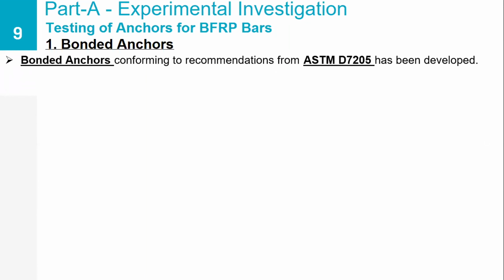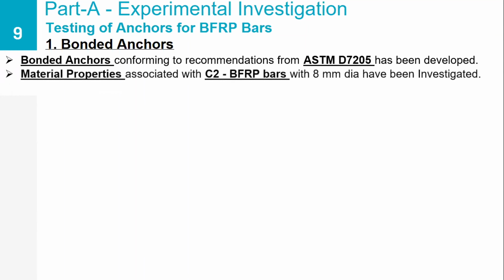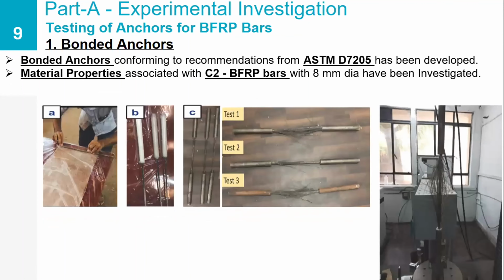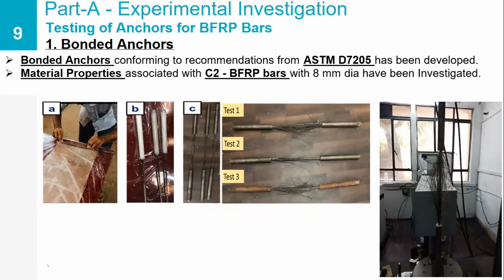So the bonded anchors were fabricated as per the recommendations of ASTM D7205, which is for any standard FRP bars. And the material properties associated with the BFRP bars of 8 mm diameter supplied by the C2 supplier have been investigated. These pictures show you the fabrication of the bonded anchor using some glass sheets which have been wrapped around the bars, and then they have been heat treated, and eventually an aluminum tube has been inserted to develop these bonded anchors.